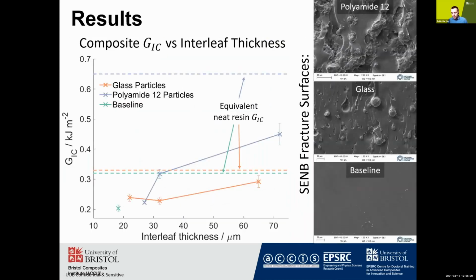So here we see a plot of interleaf thickness against mode 1 critical energy release rate, where the orange line is for interleaves containing glass particles, the blue line is for interleaves containing polyamide 12 particles, and also plotted is the baseline value in green, for the baseline interleaf value. Also plotted are the critical energy release rates from testing the equivalent neat resins.